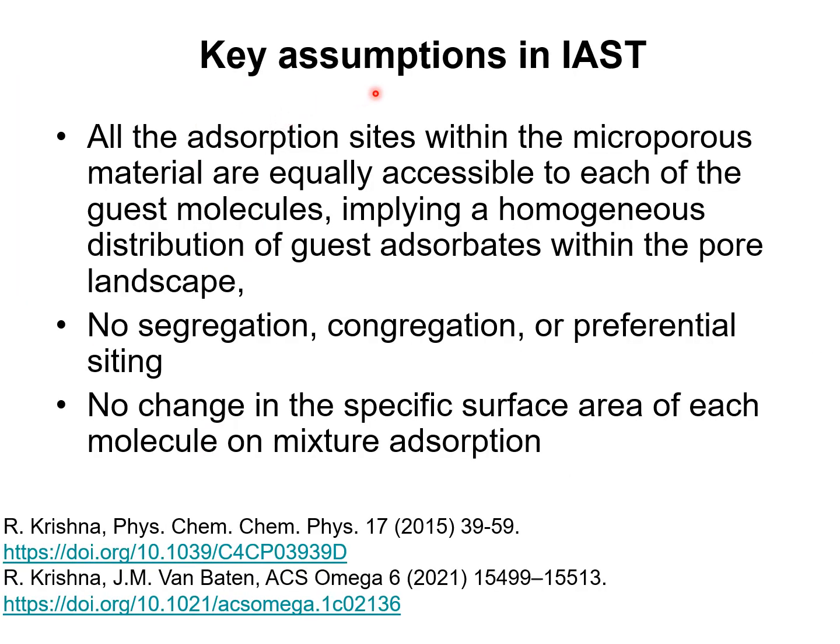We summarize the key assumptions that are made in development of the IAST. All the adsorption sites within the microporous crystalline material are equally accessible to each of the guest molecules, and this implies there's a homogeneous distribution of guest adsorbates within the pore landscape.